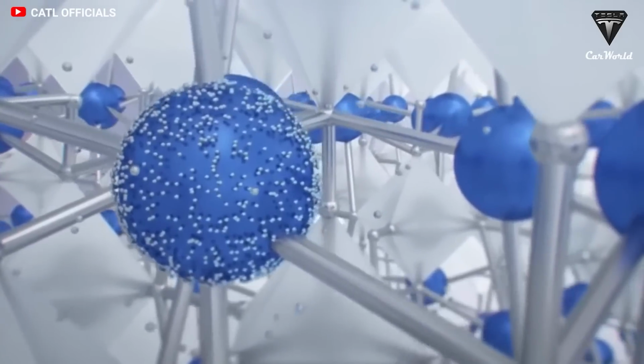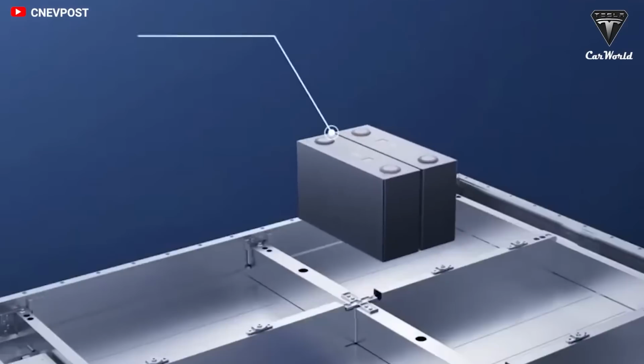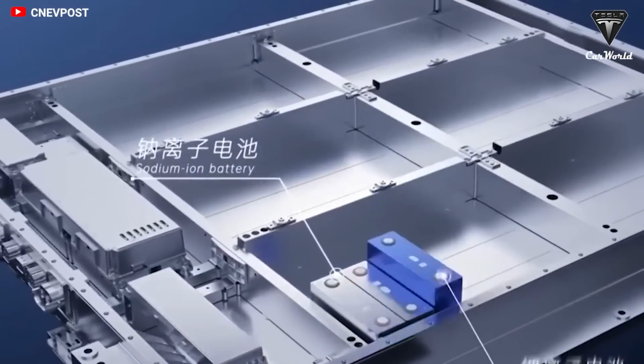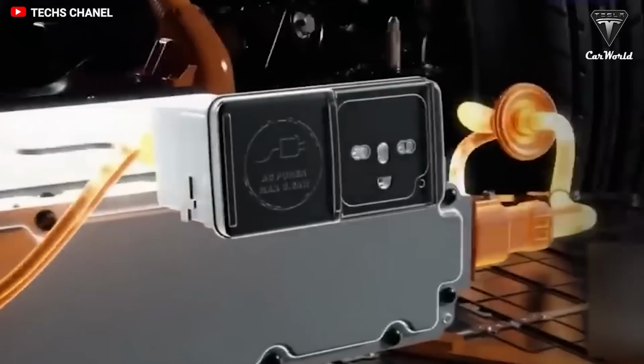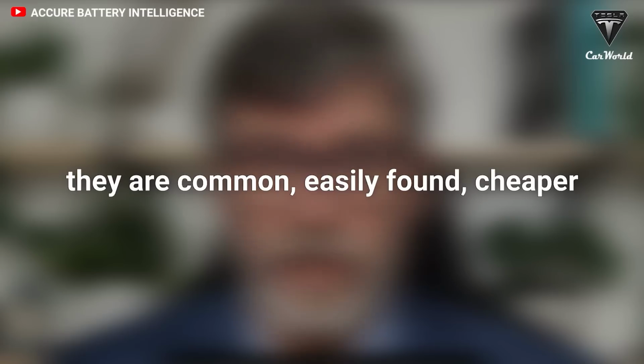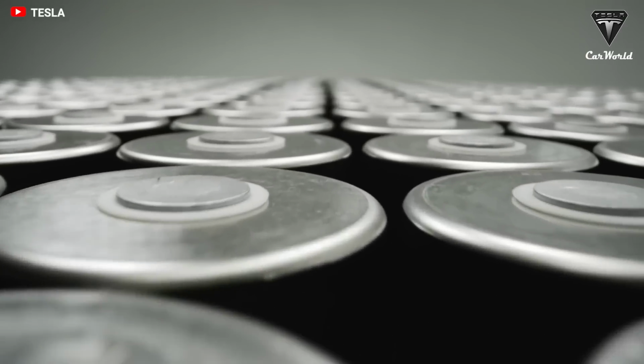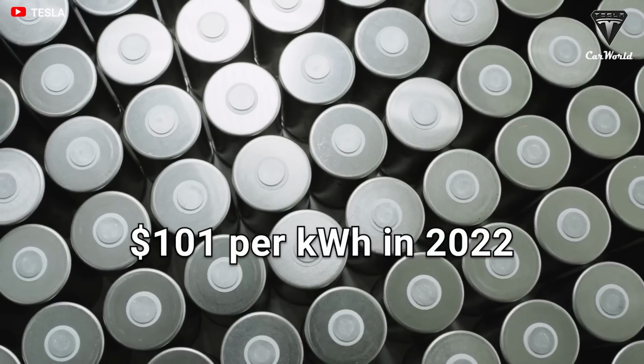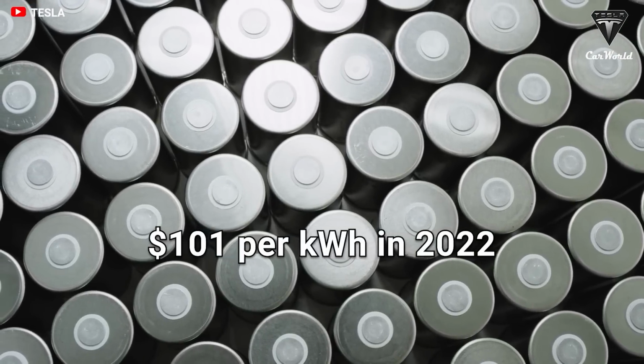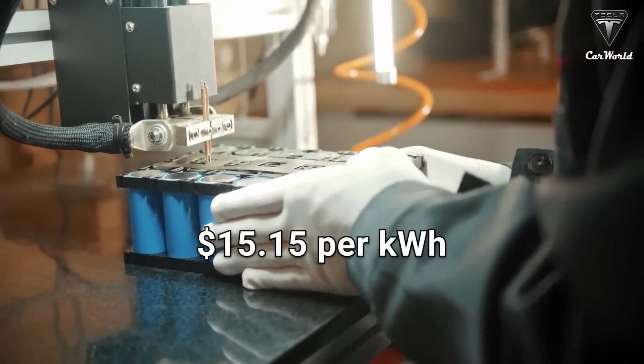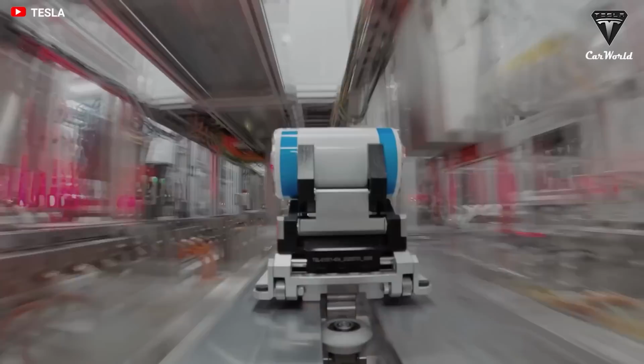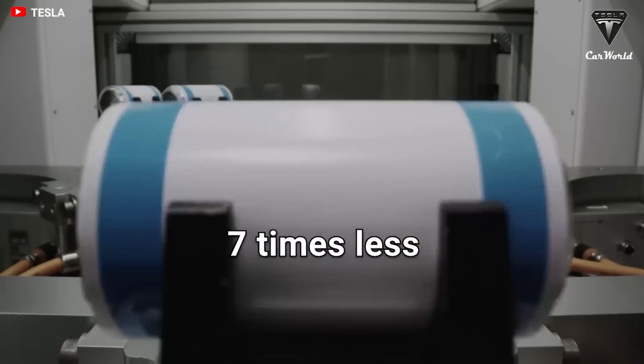CATL even said that sodium has better conductivity and that the concentration of the electrolyte can be reduced, which also reduces the cost by about 85%. And they're more common, easily found, cheaper. Those are the advantages. The average price of a Tesla 4680 battery pack will be $101 per kilowatt hour in 2022. We can then use this to calculate the new battery costs, which is roughly $15.15 per kilowatt hour, or nearly 7 times less than the 4680 battery.